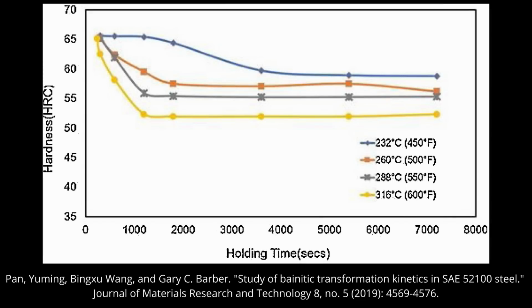But this is a way that you can determine how long it takes for your steel at your given austenitizing temperature to transform. So your steel, your austempering temperature, your austenitizing temperature, and you can see, okay, the hardness is no longer changing after about 2,000 seconds.